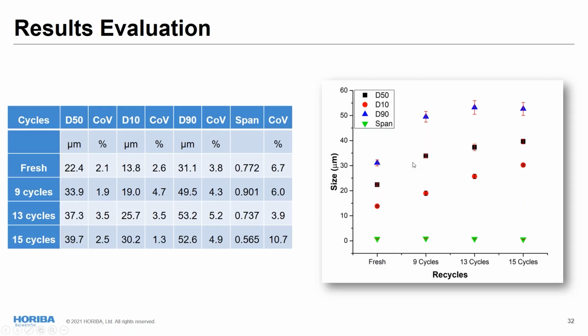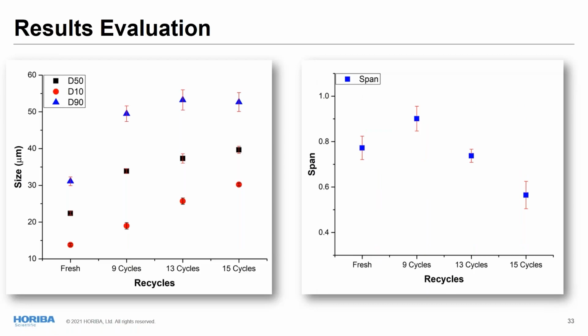And I have in this plot all the D10, D50, D90, and the span, so we can track how much we shift, and we can clearly see as we increase the cycling how much the standard deviation increased. But the proper way to evaluate those 4 numbers is to plot the span separately, because of the scale, it may give you a false impression. So first, let's look at the sizes. And we see here the D50 was black. All the sizes had an increase.